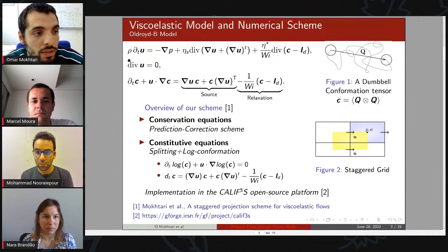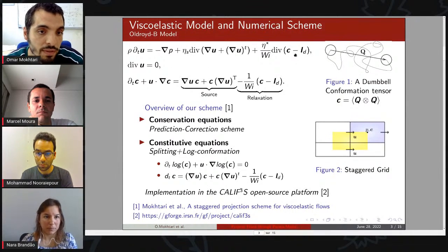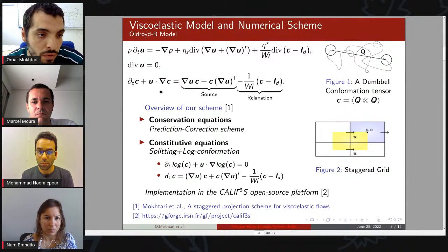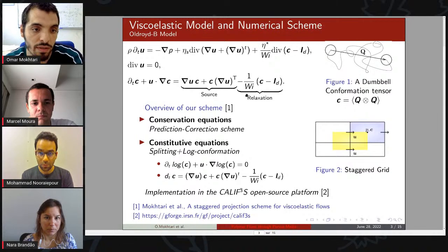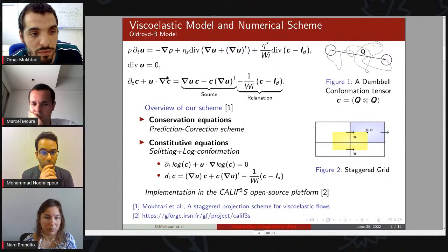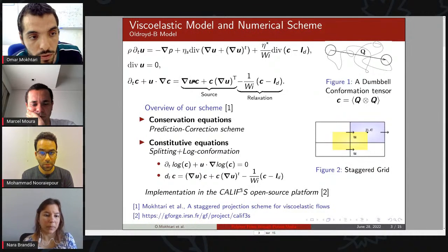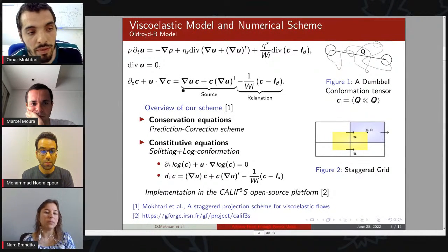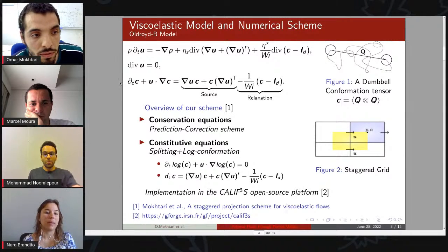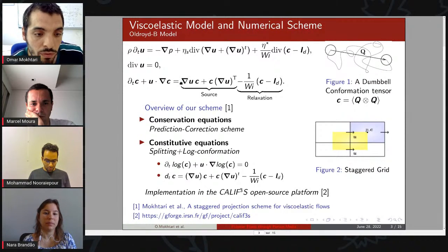So the flow is described by the Navier-Stokes equation with an additional term here corresponding to the stress induced by the polymer, and a constitutive law here, which is a transport equation of the conformation with a source term here and a relaxation term here. The major difficulty to solve this system is this source term, where the velocity gradient can be very sharp. So this equation is very difficult to solve.